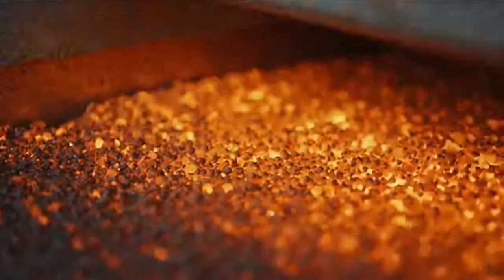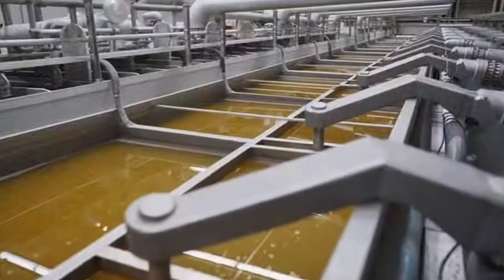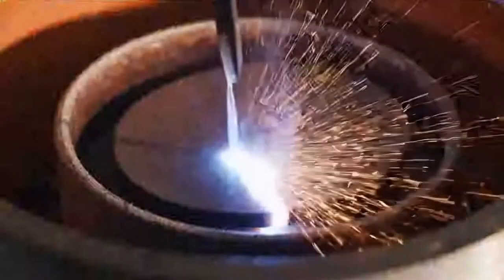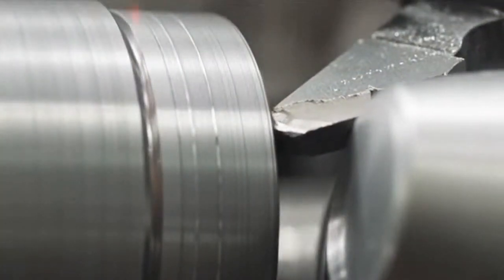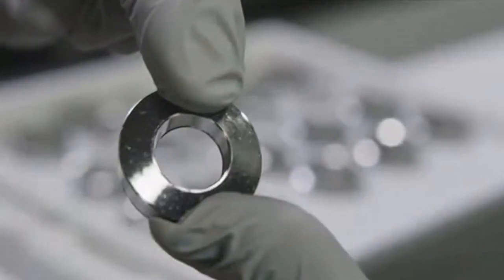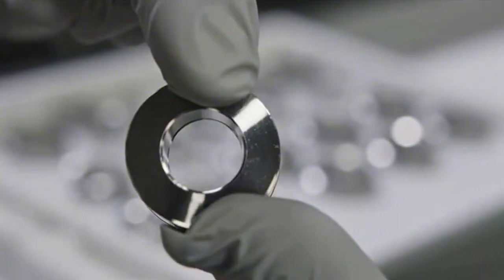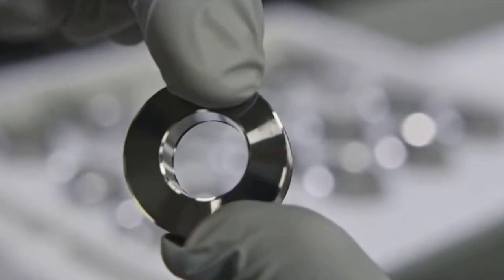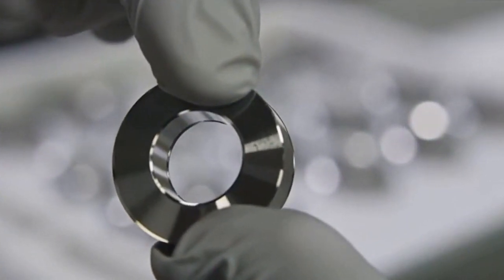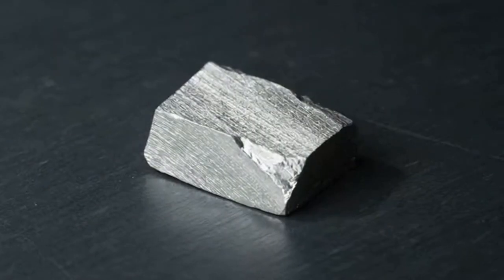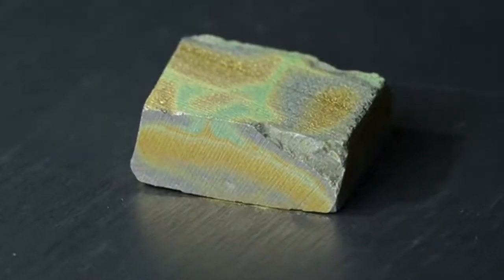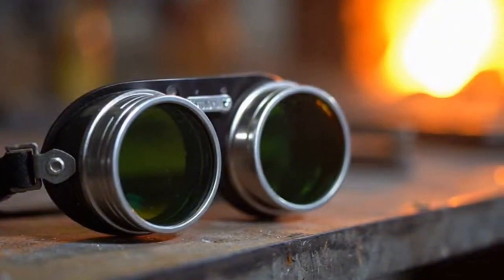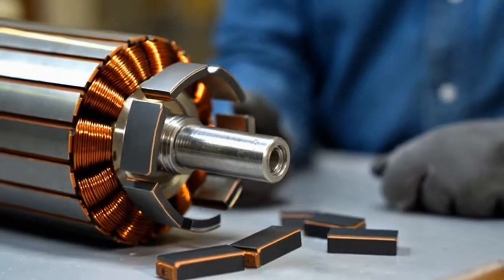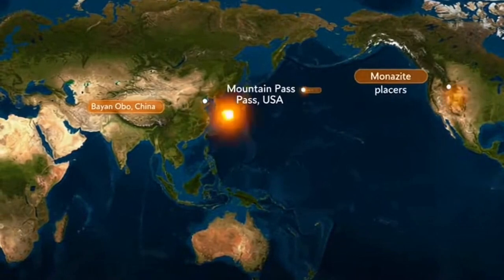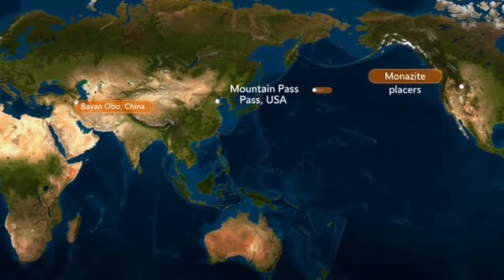Solvent extraction, hundreds of mixer settlers in long banks, like steel centipedes, is the usual next chapter. With carefully chosen organic extractants and painstaking pH control, you load the rare earth cations into an organic phase, strip them back into an aqueous phase, and repeat, over and over, inching toward purity with the patience of a watchmaker. Somewhere in those banks, cerium is pushed out early by oxidizing it to cerium 4+, which behaves differently. This is not just chemistry trivia, it is what opens the line to the twins you care about.